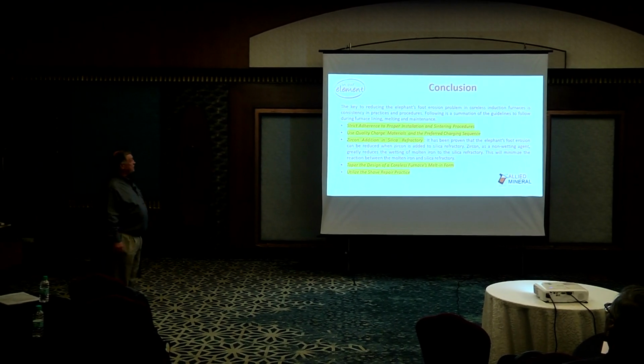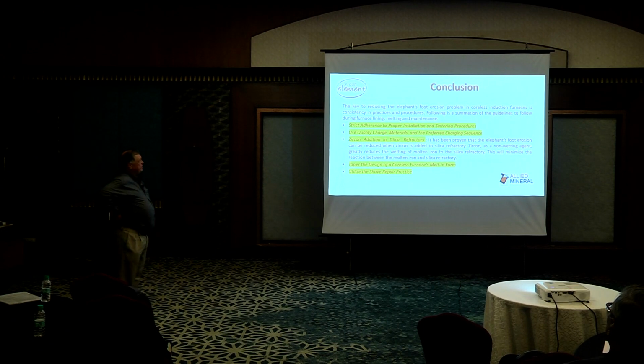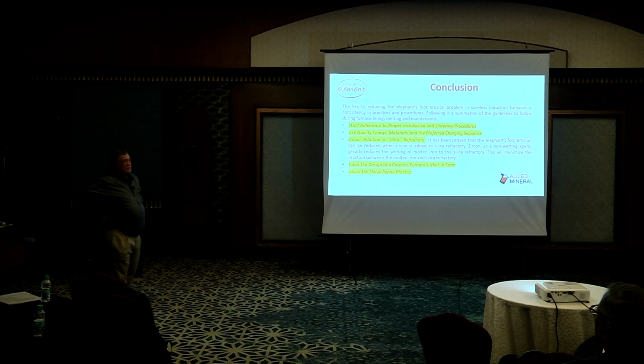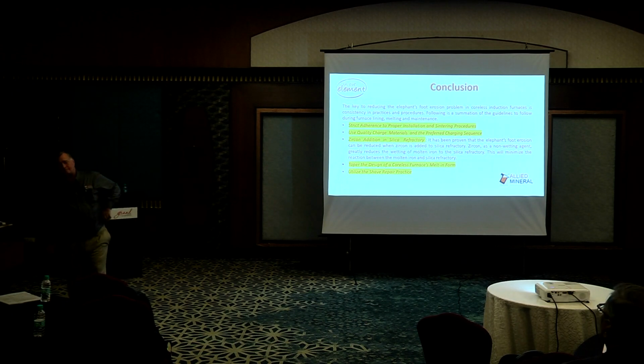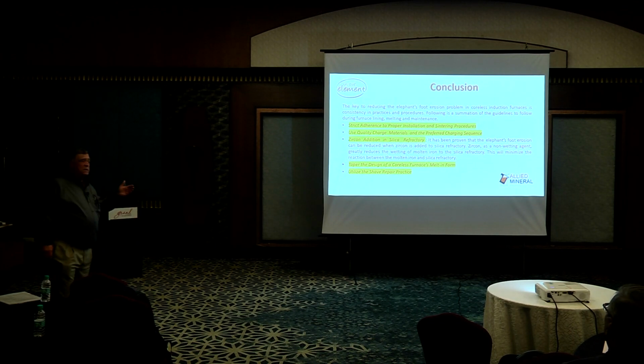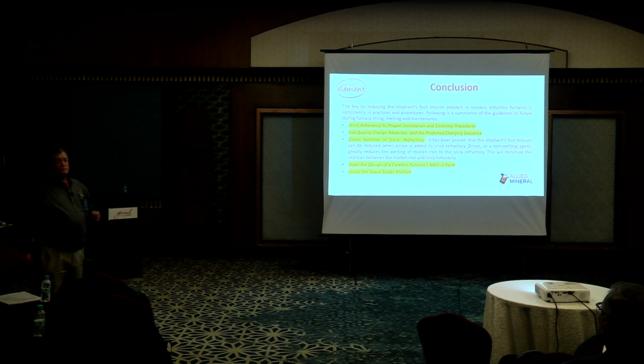Zircon addition to the silica refractory. It's been proven that elephant's foot erosion can be reduced when zircon is added to silica. Zircon is a non-wetting agent. It greatly reduces wetting of the metal to the silica refractory. I would say that it's a 50-50. Sometimes there's a benefit to zircon, people see it right away. Sometimes they don't see anything. The problem with zircon, it increases your cost. Zircon is becoming very scarce, very hard to get. The harder it is to get, the higher the price.